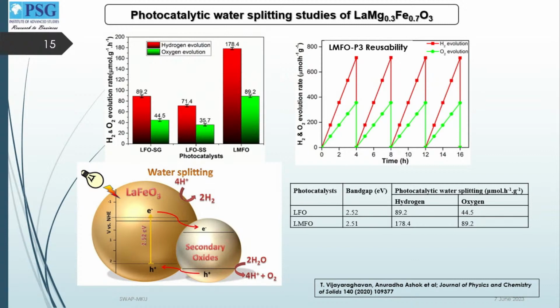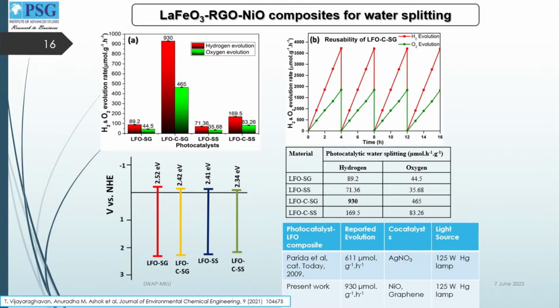Here again, lanthanum ferrite we synthesized with the sol-gel method and the solid-state method. So maybe the surface characteristics of the nanomaterials also mattered. The sol-gel synthesized lanthanum ferrite showed higher efficiency. With those we doped with magnesium. The sol-gel synthesized magnesium doped lanthanum ferrite gave better results because of certain particular surface characteristics. Probably that's why they showed better water splitting capability. So again, in lanthanum ferrite, with doping, we could achieve some improvement in the photocatalytic activity.